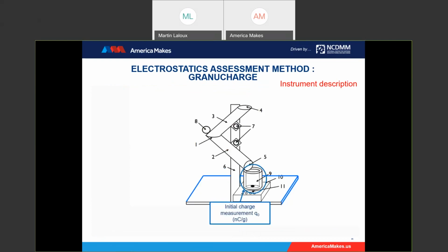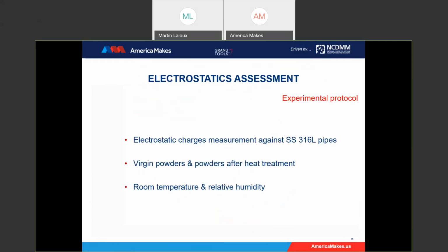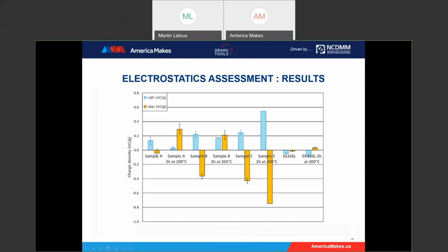To summarize quickly what I said, we measure the initial charge, the final charge, and we have the process charge. So the experimental protocol again: the electrostatic charges were measured against stainless steel 316L pipes, for virgin powders and powders after heat treatment at 200 degrees. The experiment was done at room temperature and relative humidity. First, regarding the virgin sample A on the left, it's impossible to conclude due to error bars. Stainless steel has the lowest amount of charge. It might be due to its highest PSD.